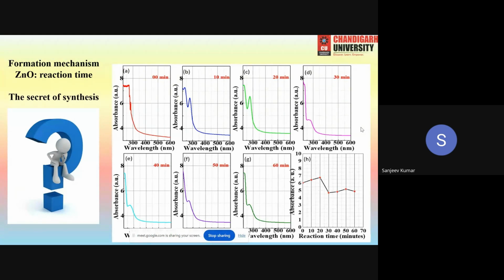Settled down means the particles become heavier in the solution and they are settling down, so the peak is not forming properly. So according to this, we can stop our reaction within 20 minutes. 20 minutes are enough to complete this reaction.